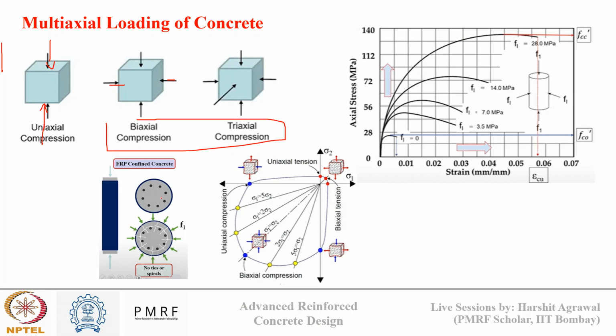So around the concrete, we use an FRP wrapping. FRP is fiber reinforced polymer. It is wrapped around the concrete and creates a confining effect, which is similar to biaxial or triaxial compression. So what is this confining effect doing? Earlier we have seen that tensile stresses are generated near the middle, which causes a concrete cylinder to fail. Now FRP provides compressive, confining stresses to the cylinder. This will resist the tensile stresses and make concrete stronger in compression when the axial load is applied. So this is the concept of biaxial and triaxial compression.